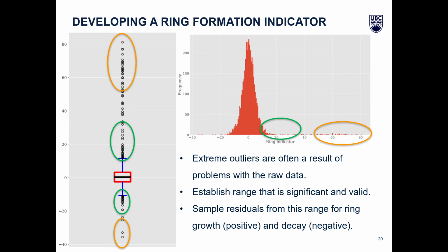We need to determine a range from which we can sample residuals that have a large magnitude, but not so large that they are extreme outliers with invalid data. The main takeaway from this slide is that our post-processing for this case study involves sampling residuals from the green circles and avoiding those from the orange circles.